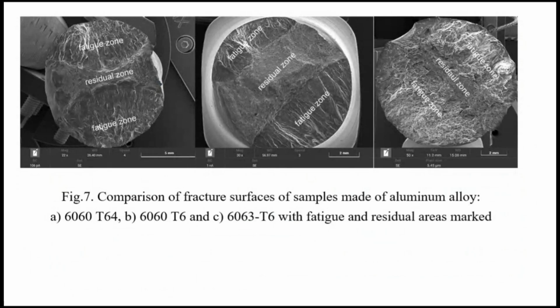On the left, you have this material as earlier, 6060 T64, next 6060 T6, and next 6063 T6. We see on every one of these photos the fatigue zone, and the middle residual zone, in this area the stress was nearly zero during the fatigue test. Initiation and propagation was from the 2 sides on the upper, and then goes to the plate without stress. So it's a typical specimen. Every specimen looks nearly like these 3, as we see on the presentation.